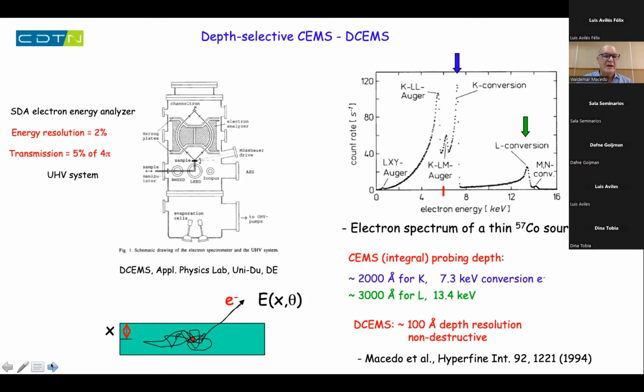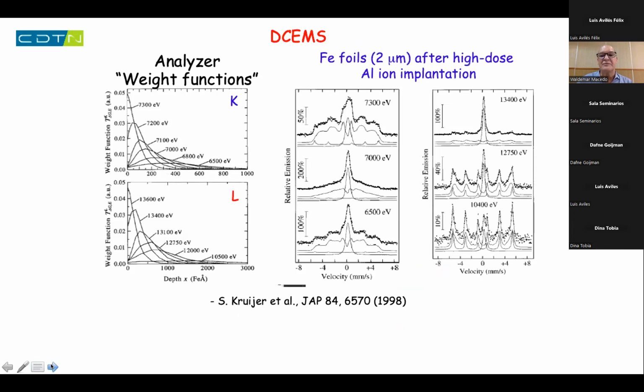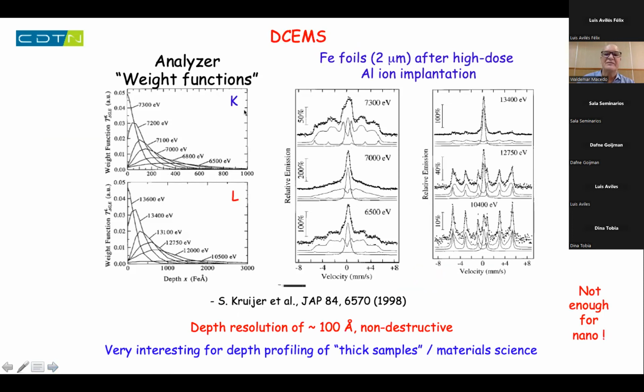This CEMS is very interesting for doing material science. In a bulk material, by selecting the energy of the electron, you can probe different depths inside your materials with this 100 angstroms selectivity, but it's very interesting for bulk samples, for material science, for coatings, things like that, or ion implantations, but it's not enough for nano, okay?